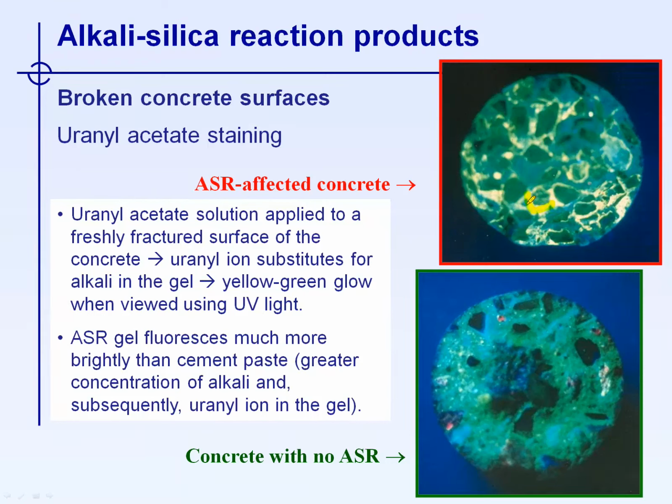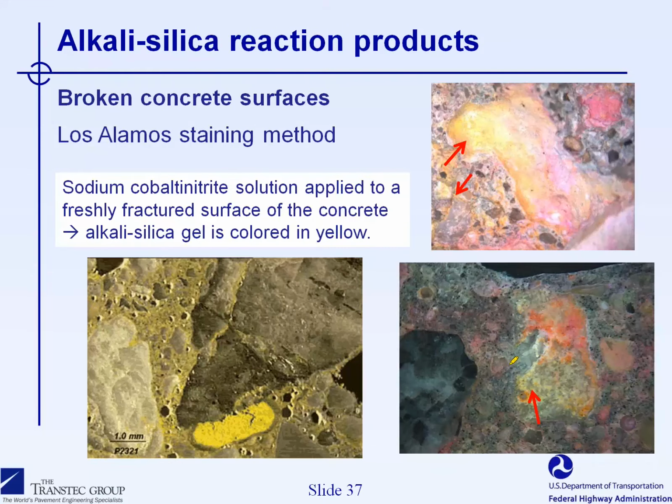And after the exposure of the cracked surface to the uranyl acetate solution, under UV light, you can see that the gel is actually glowing very well under UV light. This is a concrete that is affected by ASR, and this concrete has no ASR, so you don't see the same type of feature after the application of the uranyl acetate solution. In view of the limitations in the use of the uranyl acetate solution,